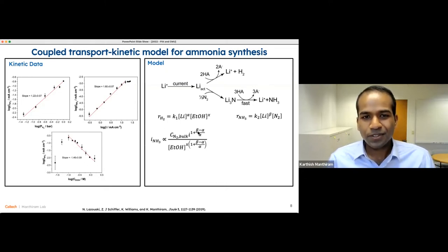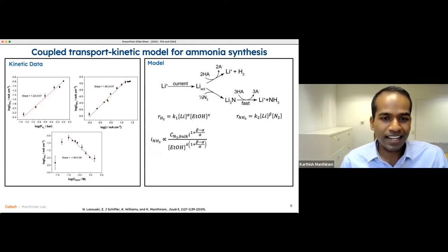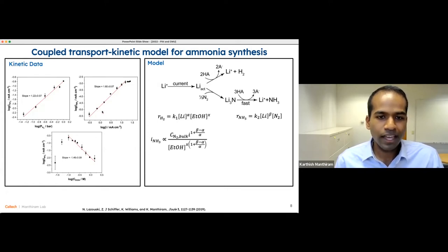In addition to that, you'll find that current and ethanol have equal but opposite order dependencies, as long as X equals 1, which is reasonable based on the model that we've assigned here. And you'll see here on the left-hand side that the order dependence on current and the order dependence on ethanol have equal but opposite order dependencies.